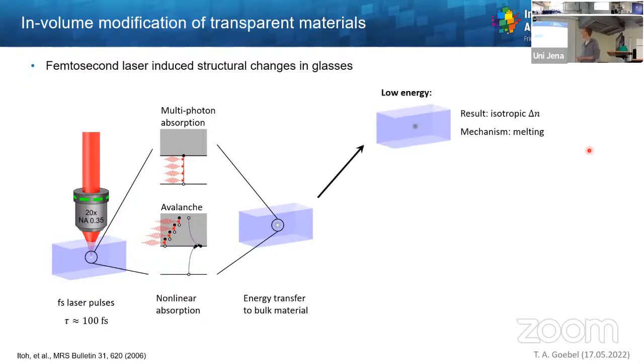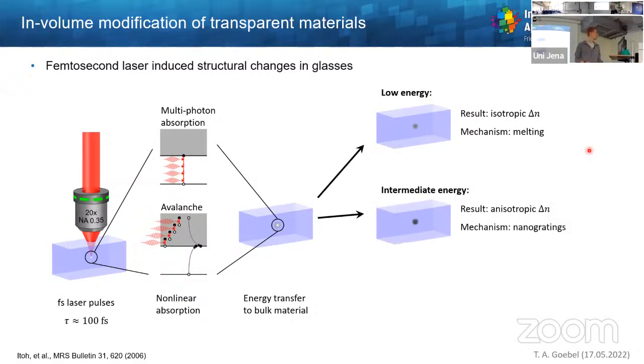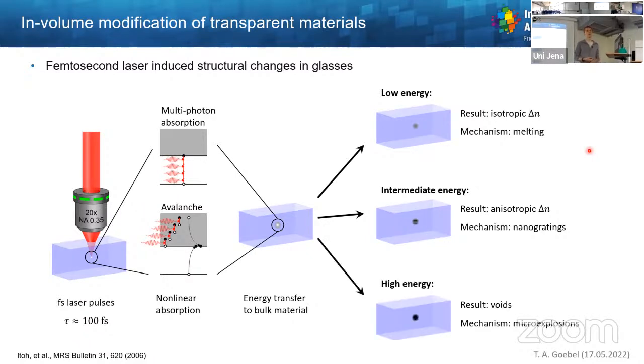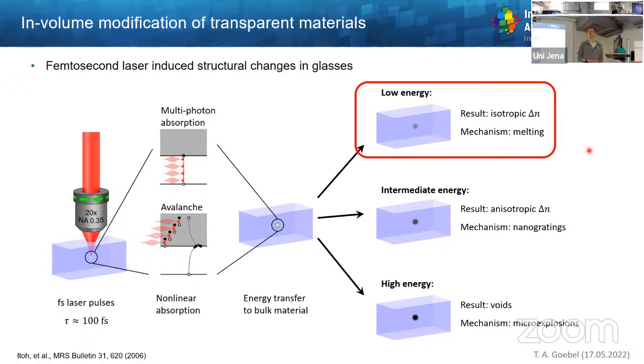So one effect is that when we are in a low energy regime, we have a constant or homogeneous refractive index change. So this is basically an effect by melting and densification due to the rapid cooling afterwards. In a second energy regime, we get a formation of so-called nanogratings, and due to this grating structure, this will cause an anisotropic refractive index change. And finally, if we use too much power, then we would end up with small voids inside the volume. However, this is not what we want to do, because in particular, the void regime is a regime where we cause loss due to scattering. So we are focusing on this low energy regime. So this is how we structure our transparent material.